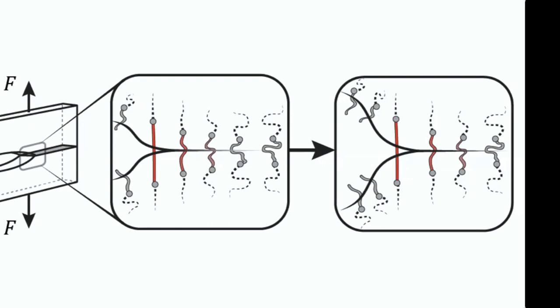Because that wear fundamentally means that I've got little pieces of material that are breaking off under repeated use. So I've got a crack, or maybe many cracks, within the material that are propagating and growing. And that crack is propagating through these long polymer molecules in this tangled mess of cooked noodles that Jeremiah introduced. And as the crack moves from left to right, what I'd like you to do is shift your perspective here and think about what's happening to the molecules that are involved.